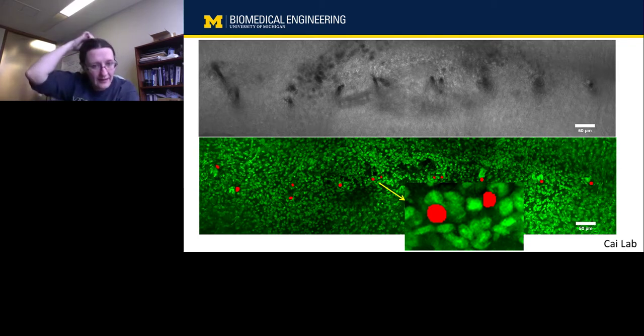So now we can take those black dots, and we know where the electrodes are on our other images. And now you can combine these slice-in-place electrode positions with any staining of your choice. And as part of our Brain Initiative project, we're trying to put together a menu of stains that you can use in combination with the carbon fibers. So red dots here are electrodes, and the green dots here are neurons. And importantly, this is 11 weeks after implant. So any scarring process that was going to happen should have set in by now.